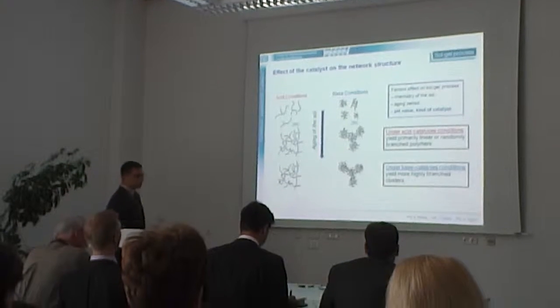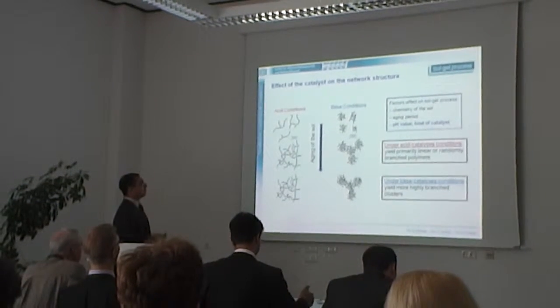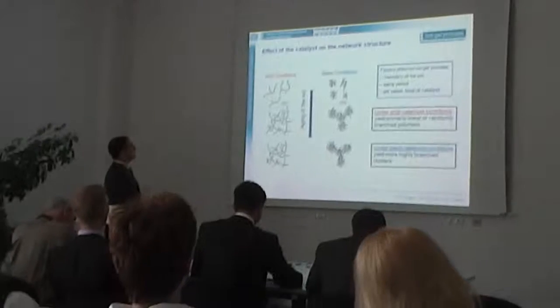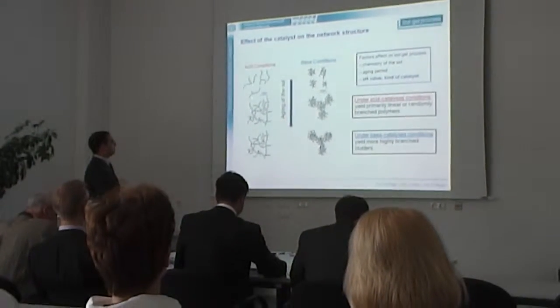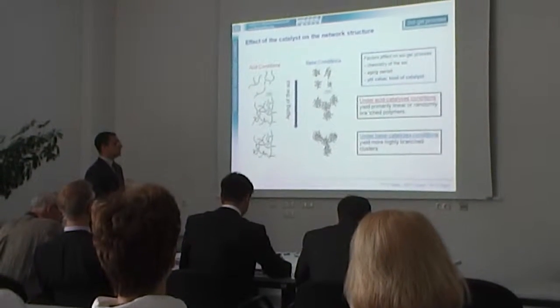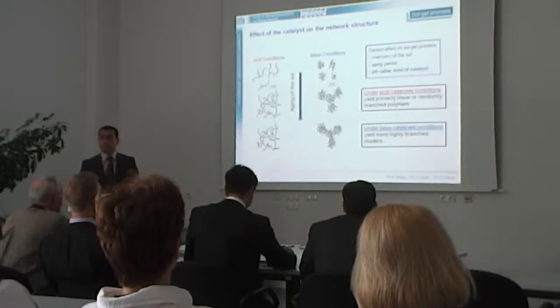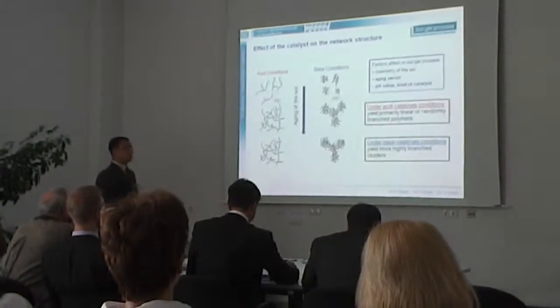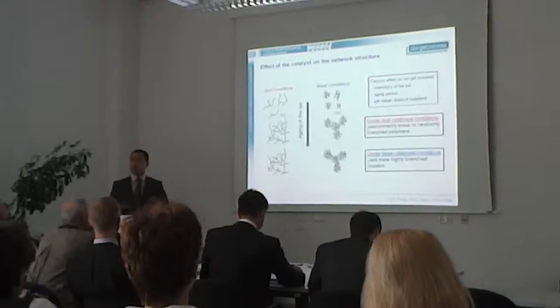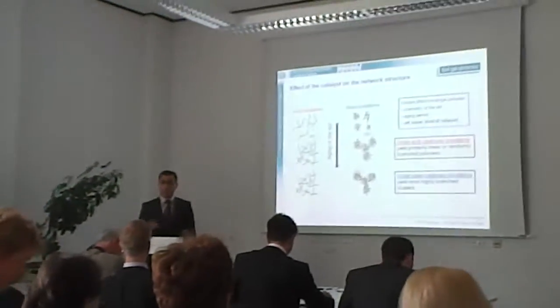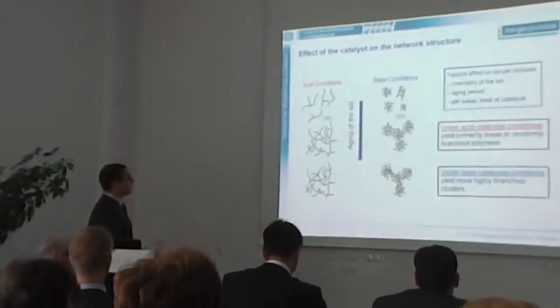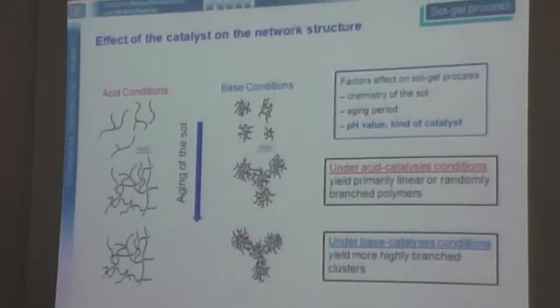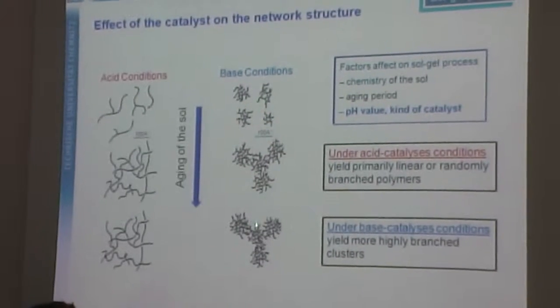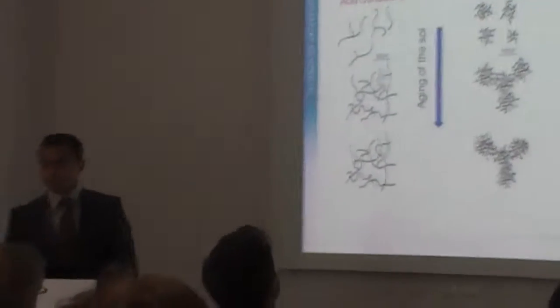The third factor that can affect the sol-gel process is the kind of catalyst. In the case of acid catalyst, the polymer is linear, and the silicate films prepared by acid catalyst are dense and have important protection. In the case of base conditions, clusters are formed and there are pores between these clusters. And therefore, silicate films prepared under base conditions have no protection.